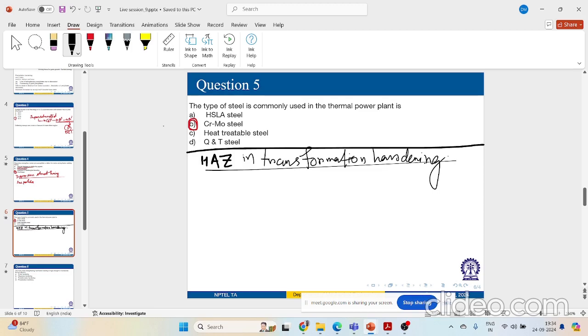Now, the weld thermal cycle that will be imposed during welding and that imposed during conventional heat treatment of steel are completely different, right? I mean, during welding, you are going beyond the melting temperature of steel. What is the melting temperature of steel? It is above 1500. While doing heat treatment, you don't go beyond the A1 or A3 critical upper critical temperature for austenite formation, right? That is somewhere around 900 degrees. So the weld thermal cycle experienced during welding and during the heat treatment process is completely different.